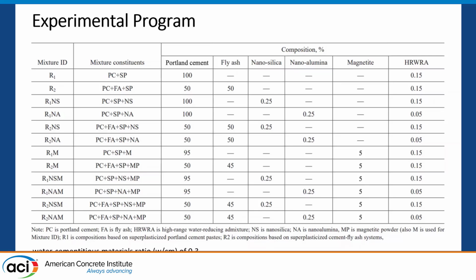experiments we ran also, in addition to nanoparticles, we like to add fly ash, and we also tried magnetite particles. So in addition to nanoparticles, which were used in very small dosages, magnetite is not really an exotic material to us. It is a black pigment which we use for architectural concrete. And usually 5% is the normal dosage if you want to change the color of concrete to a desired shade. And so magnetite, again, is more expensive than Portland cement, but it is something which is in our toolbox, which we use in concrete technology. And again, it is a highly magnetic material, and it is an attractive component.